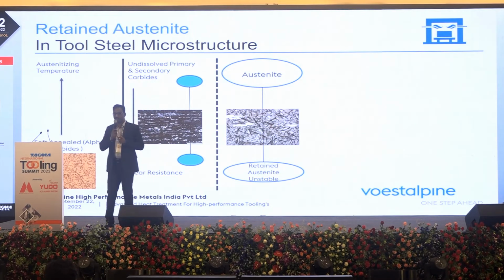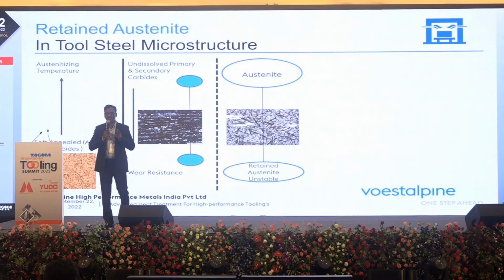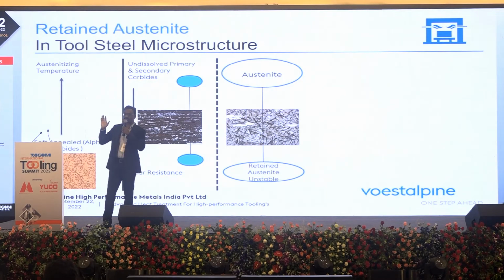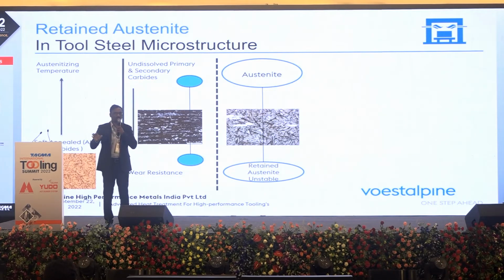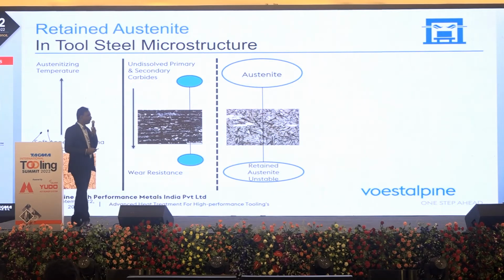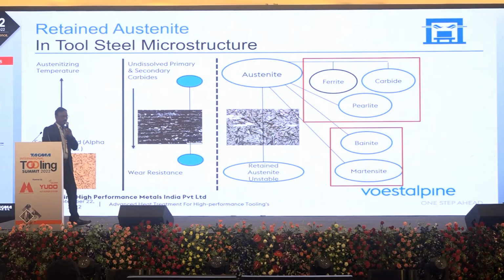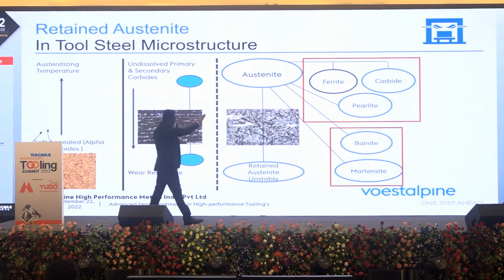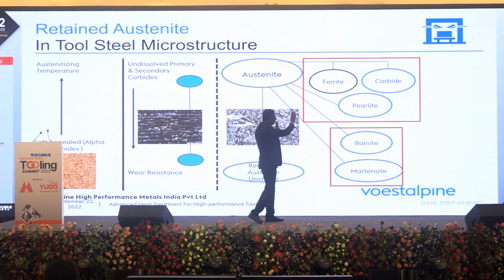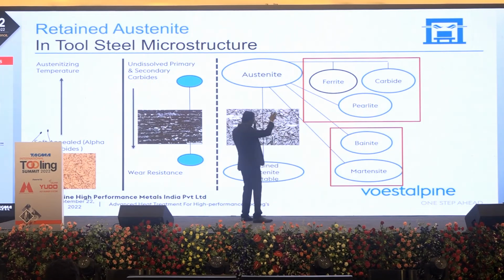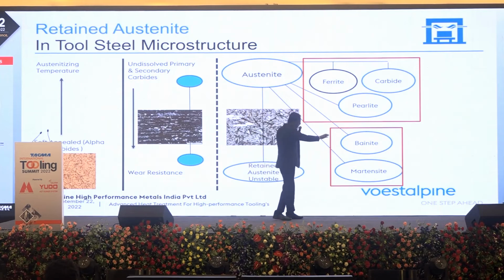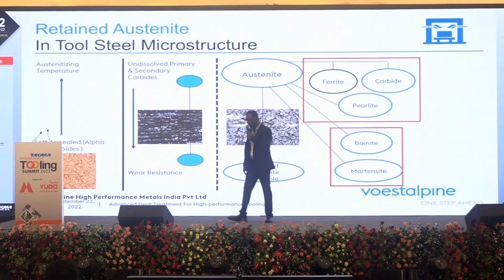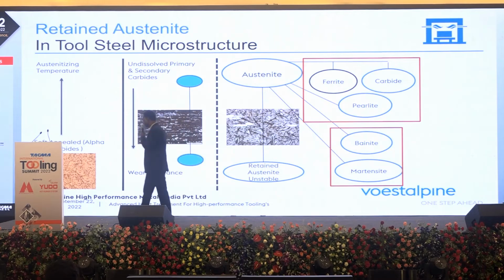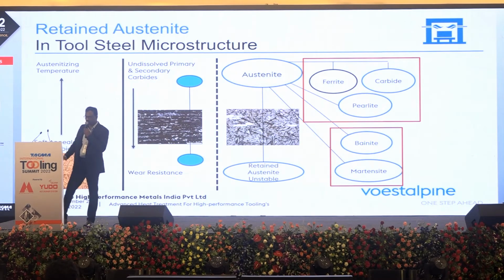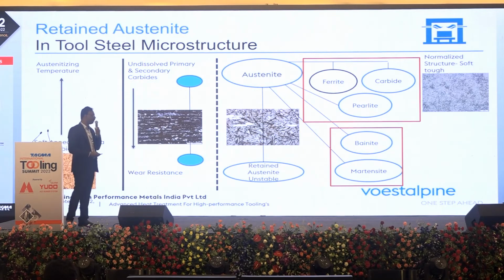How to control it? We need to measure this. How to measure this? There are certain limitations in the measurement. Up to 1 or 2%, that is away from the detection limit. So we need to ensure it is reduced to close to 1 or 2% to get the maximum out of it. As I said, if you cool too slowly, byproducts such as ferrite, carbide precipitation and pearlitic structure will form. If you cool a little faster, you may end up with bainite, upper and lower. And if you cool drastically, as fast as possible, you end up with a martensitic structure, which is the intended microstructure for our heat treatment.